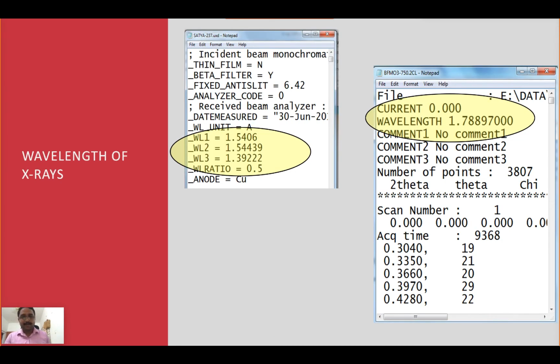Another important aspect will be the wavelength. Here you can see the wavelength 1.7889. I think it belongs to a cobalt target, not molybdenum, cobalt target. They have issued only 1 K alpha. But in another data what I have seen is, you can see wavelength 1 is 1.5406, wavelength 2 is 1.54439, and wavelength 3. You can see that wavelength 1 and 2 are K alpha 1 and K alpha 2. The ratio they have given is 0.5. The third wavelength is K beta, which has been filtered.